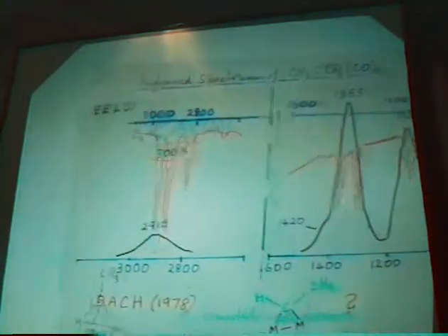But when we did further work with the CD3 compound, we showed that that assignment did need reversing and it fitted together. And so by that means, with the help of the metal cluster compound, we were able to say, yes, that spectrum corresponds to what we nowadays call the ethylidyne species. Some people call it the notorious ethylidyne species, but it's a famous spectator species to a catalyst man.